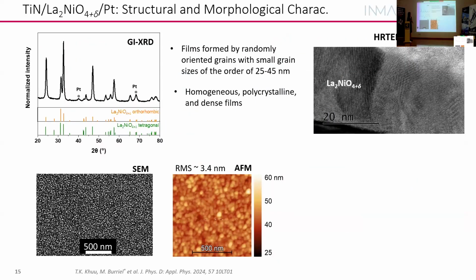Okay. So these are our thin films. We deposit on platinum substrates. There's no epitaxial relationship, so we have polycrystalline thin films, which we see here by SEM. The roughness is about 3.4 nanometers. And we have the expected phases, polycrystalline peaks by XRD.